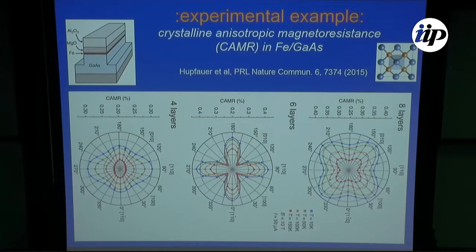So with 8 monolayers of iron, we could claim, based on this experiment, that the proximity spin-orbit coupling is gone. Essentially, you have bulk iron. I think this is a really beautiful experiment, for the first time showing this transition from interface property to bulk property. And it's very important, I think, in the physics that you discuss.